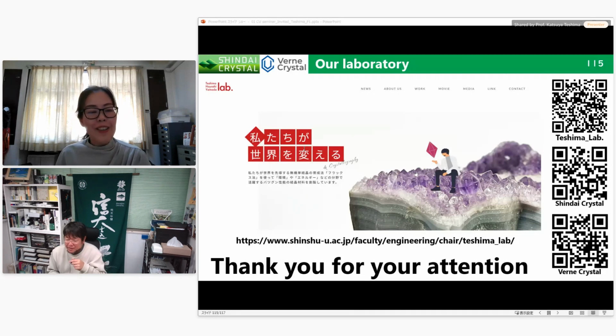Thank you, Sensei. Any other question from the audience? When you mentioned the crystal, and then the high performance of the flux-grown crystal such as LCO compared to the commercial particle, I just wonder whether the reason it has higher performance is because it has a certain orientation of the crystal that matches the preferred diffusion path of the lithium, or because you have a lower amount of grain boundary. What is the main reason that your flux-grown crystal has much better performance compared with the commercial one?